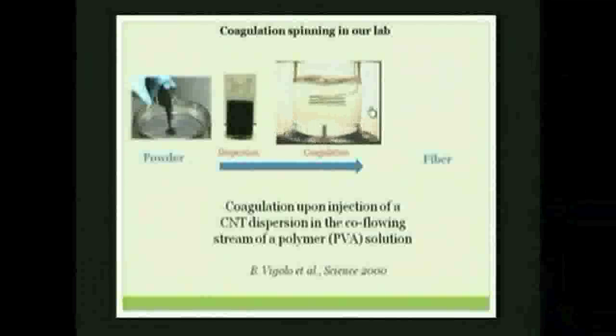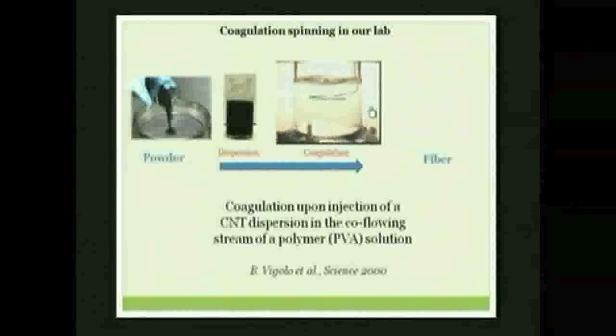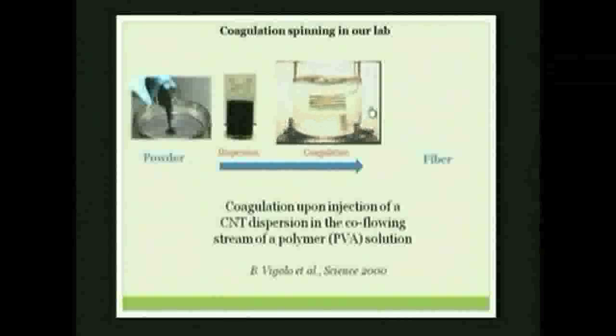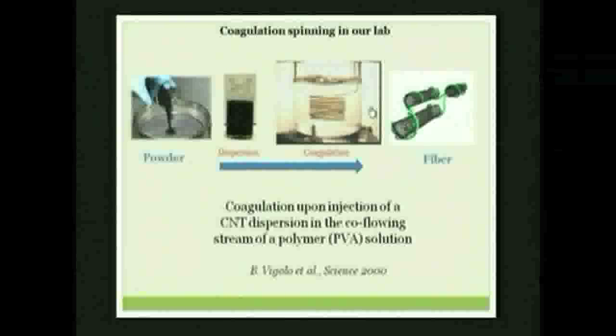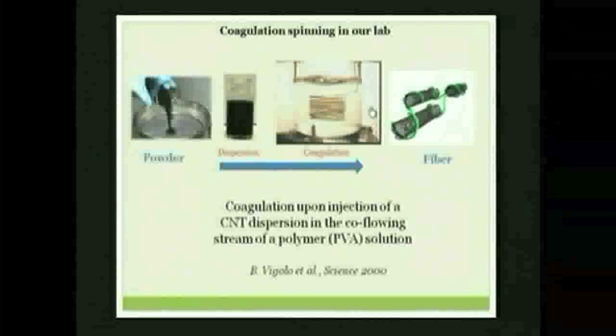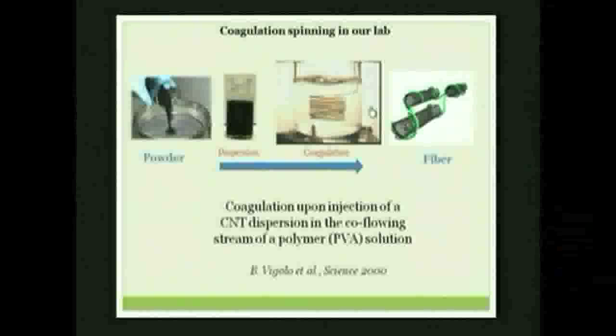So what happens when the nanotubes come in contact with the coagulating fluid? The polymer inside this fluid will replace the surfactant on the surface of the nanotube, and then the chains, which are rather long, will bridge the nanotubes together like what you see here. And then you can make a macroscopic fiber in which you have carbon nanotubes embedded in a polymer matrix. Okay? So it's a very simple coagulation process using water, using a simple polymer, and we patented this in 2000.